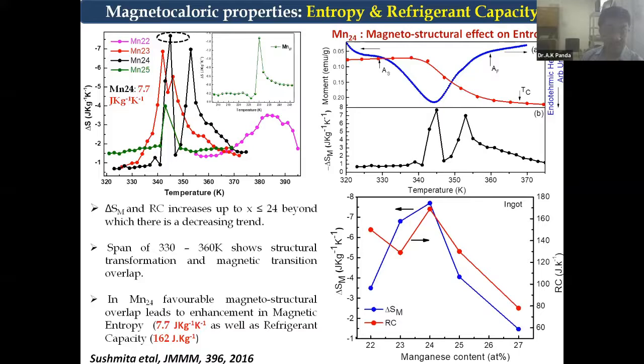So this is how we try to optimize the composition for this set of alloys, and it is around a span of 330 to 360. And what you find is Mn24 shows an enhancement of magnetic entropy of around 7.7 joules per kg Kelvin and a refrigerant capacity of 162 joules per kg. So this is how the materials are characterized and the properties are evaluated.